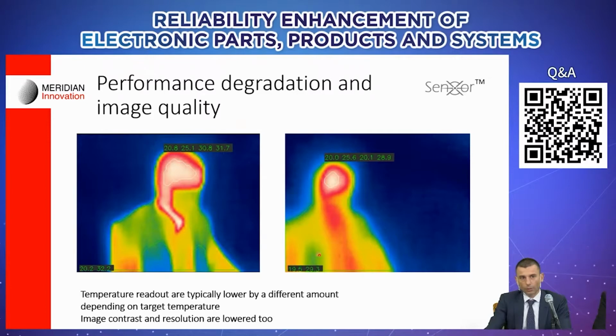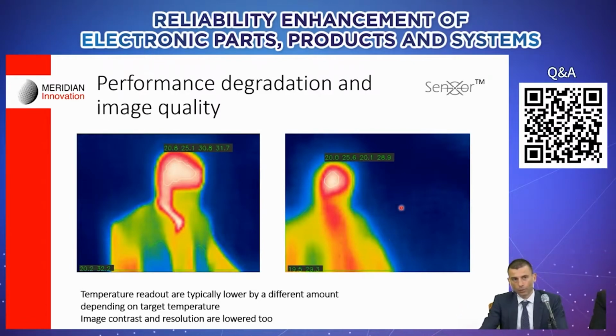And in the other case is an image which was taken with a sensor that has degraded both in terms of lens and sensitivity. So you can see the transition between the hotter object, which is the person in this case, and the ambient background is a lot broader. So you lose both resolution in a way, focus, and the temperatures are appreciably lower as well as a result.